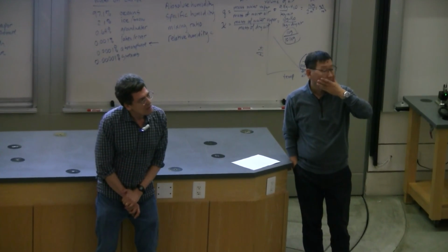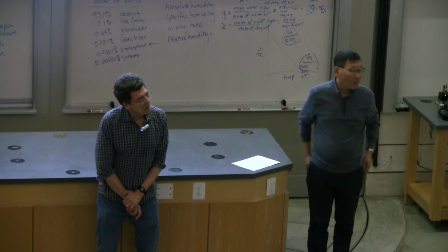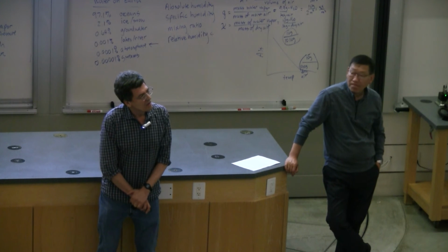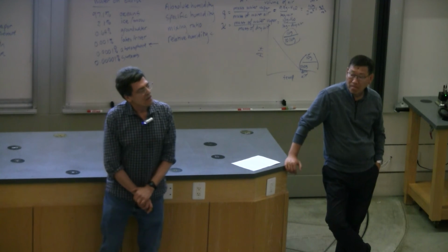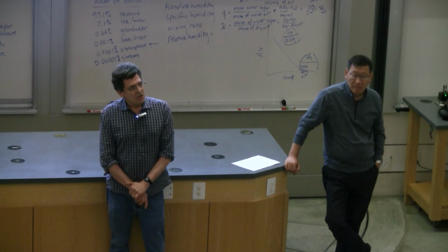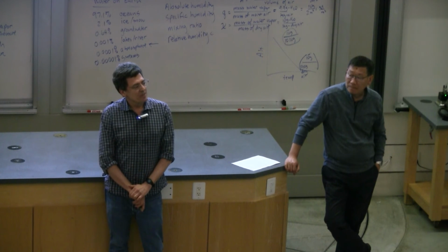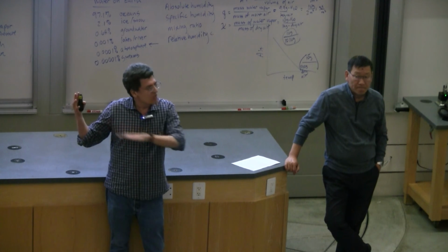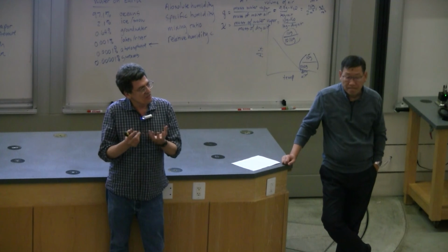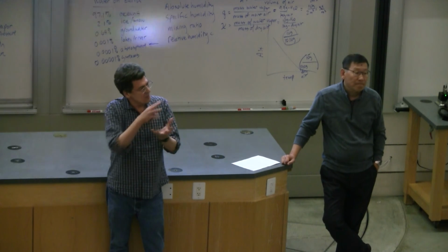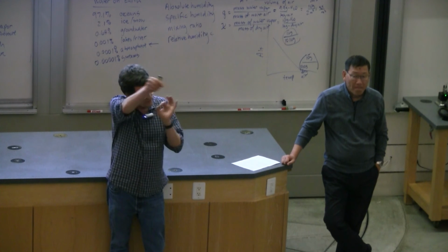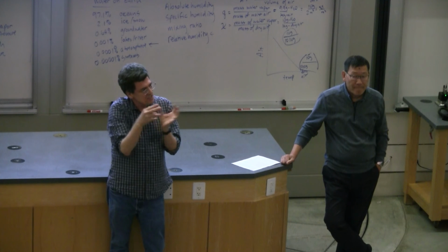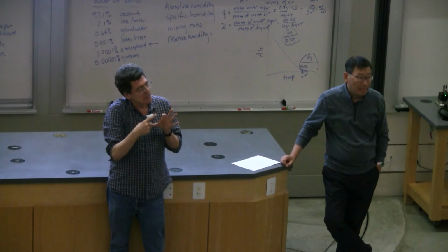I would like to ask how robust is the Wigner crystal to different kinds of perturbations? Let's say there is no uniformity in the Moiré structure, or there are different strains. How does that affect the stability of these phases? Okay, I can answer that question best for the generalized Wigner crystal; defects help stabilize it for the single layer, but for the generalized Wigner crystal, those different phases were pretty robust. We have to find a defect-free region to see it. If the defects are too dense, we're not going to see it. But if we get a couple hundred nanometers to a side, we can see it.